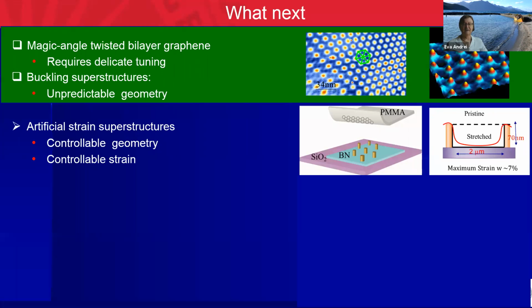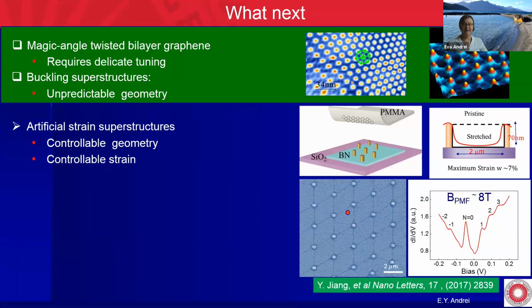So we have done this with this structure here, and we found a very nice pseudomagnetic field. Here we have 8 Tesla. You see the pseudo-Landau levels give you a pseudomagnetic field of 8 Tesla. When you go on top of these pillars, the fields become huge and the strain becomes huge. It gets close to the breaking point of graphene, close to 20%, and very interesting things happen on top of these pillars. But the bottom line is perhaps this is the way to go next, to take this direction forward.